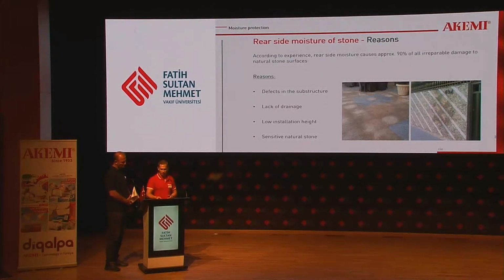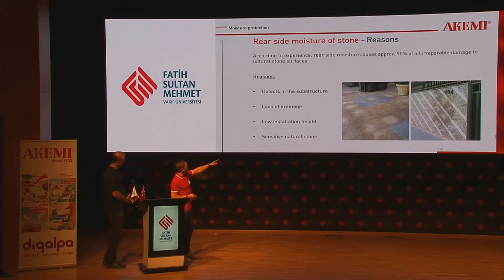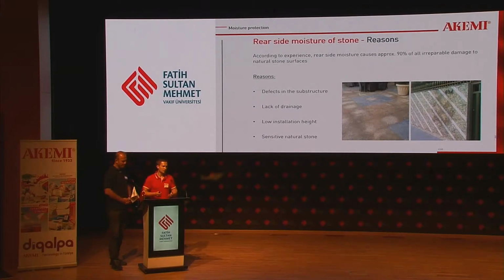And here you can see also a very interesting picture, because this is in the desert of Abu Dhabi, or of an Arabic country, and this is all stained. The whole area is a huge stain. Only the light and bright colors are not stained. And you cannot clean this because the salt and efflorescence destroyed the complete stone. So they have to break it up and build it new. We have no chance to clean this anymore. And the reasons are defects in the substructure or something like that, but water always goes into the stone if it's not protected from the backside.